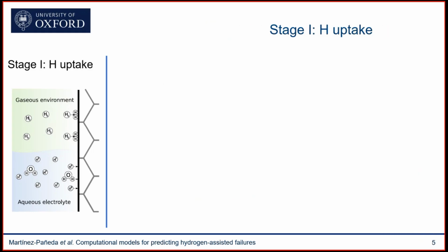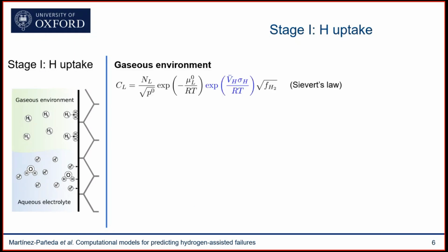So let me start with the hydrogen uptake. As I said before, the goal here is to quantitatively relate a given environment, it could be a gaseous environment or an aqueous electrolyte environment, with a hydrogen content at the surface of the metal, or a hydrogen absorption. And I think the good news here is that when we are dealing with gaseous environments, this is relatively well understood, particularly if we're talking about, you know, steady state conditions. Kinetic effects are another business. But if we're talking about steady state conditions, then we know that in gaseous environments we can use a closed form expression, Sieverts' law or the Abel-Noble equation, to obtain an estimate of the hydrogen concentration at the surface of the metal as a function of the hydrogen pressure or fugacity.